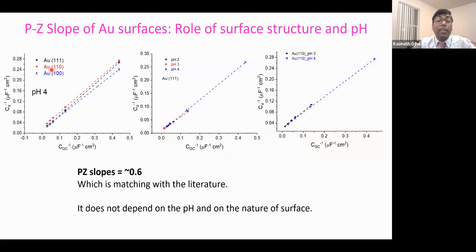So here, on platinum, I cannot do different surface measurements, because in the double layer region that I showed you in the CV of the platinum 111, on the other facets we don't find a clear double layer region. That's always overlapped with the specific adsorption region. So we won't be able to get ideal data, so we don't do that.